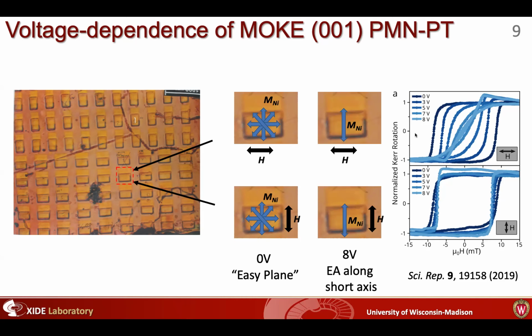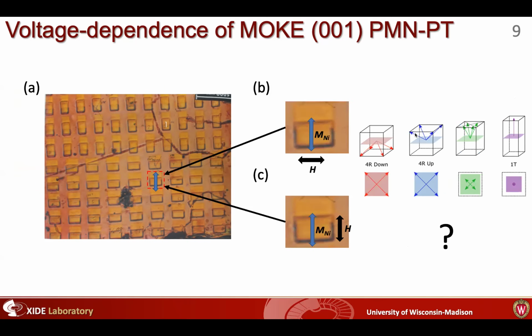Initially we had used a wet etching procedure that gave us really low yields. So the xenon difluoride etching, which allowed us to have many more electrodes, was actually a very big jump in our productivity. So once I was able to test this on multiple electrodes with other orientations, we found, oh yeah. So again, I just want to highlight in the rhombohedral to tetragonal transition, we should only expect isotropic in-plane strain. So it's kind of a surprise that we see this manipulation at all.